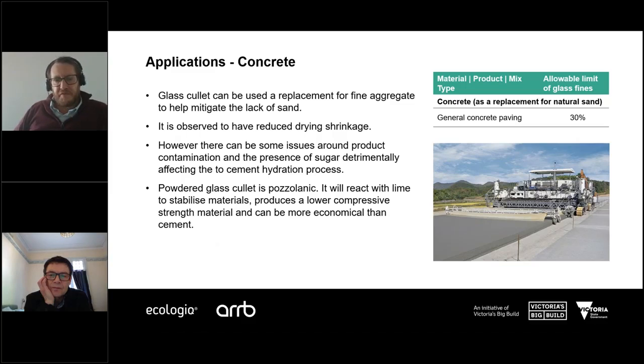We do need to be mindful of contamination in recycled crushed glass if we're incorporating it into concrete, particularly around the presence of sugars, which obviously are quite prevalent in the container glass that's used for both food products and also drinks bottles. So the presence of sugar is quite detrimental to the cement hydration process. And obviously the cement hydration process is what gives concrete its strength. So it's important to use clean glass when we're incorporating it into concrete, so that we don't detrimentally affect that cement hydration process.